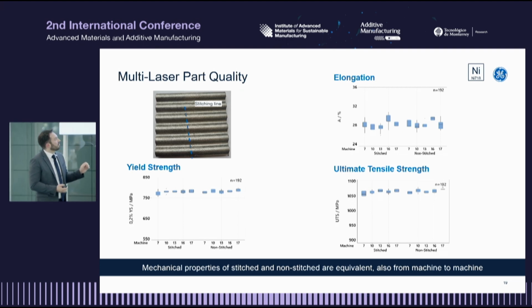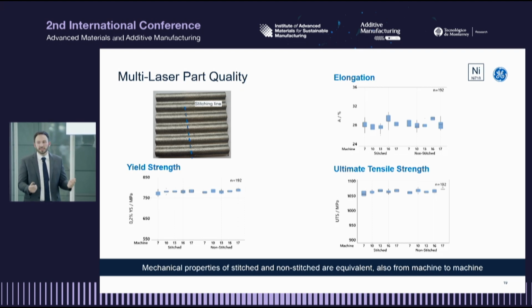So we've put together a series of box plots where on the left-hand side of every graph is the stitched version, and on the right-hand side is unstitched or bulk material. Without running statistics, and they'd be quite easy to run, we can just visually see that these 192 specimens that were tested in nickel 718 show really similar behavior between the stitched and the unstitched regions.